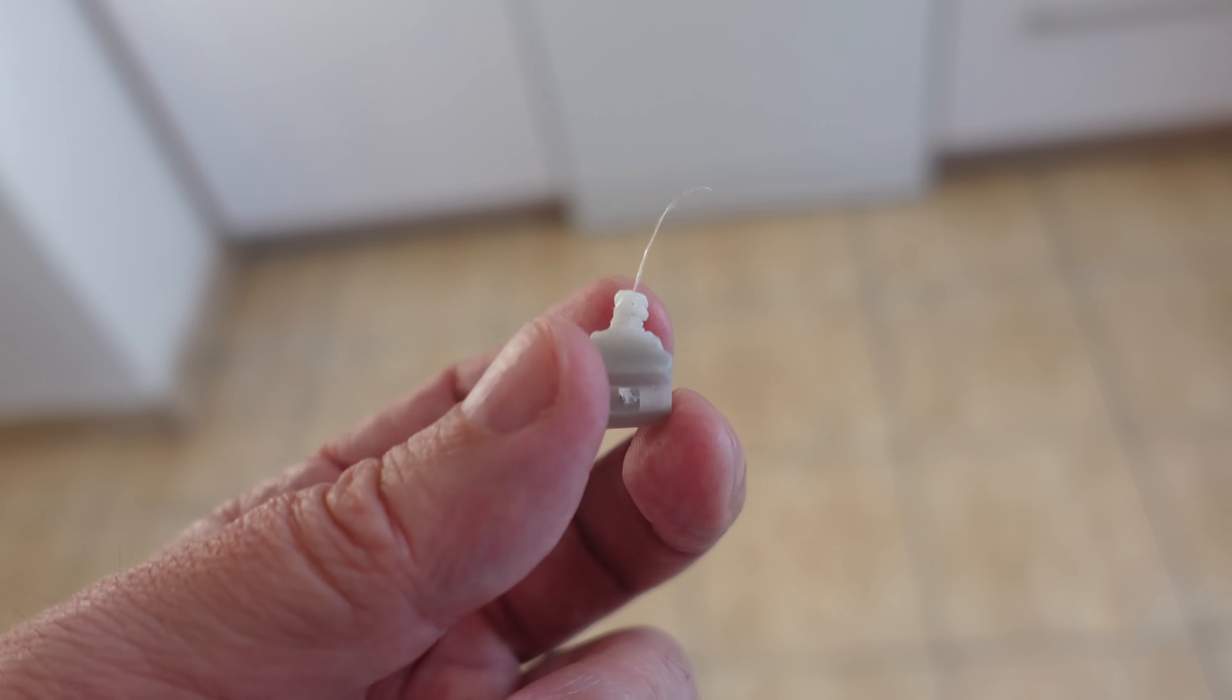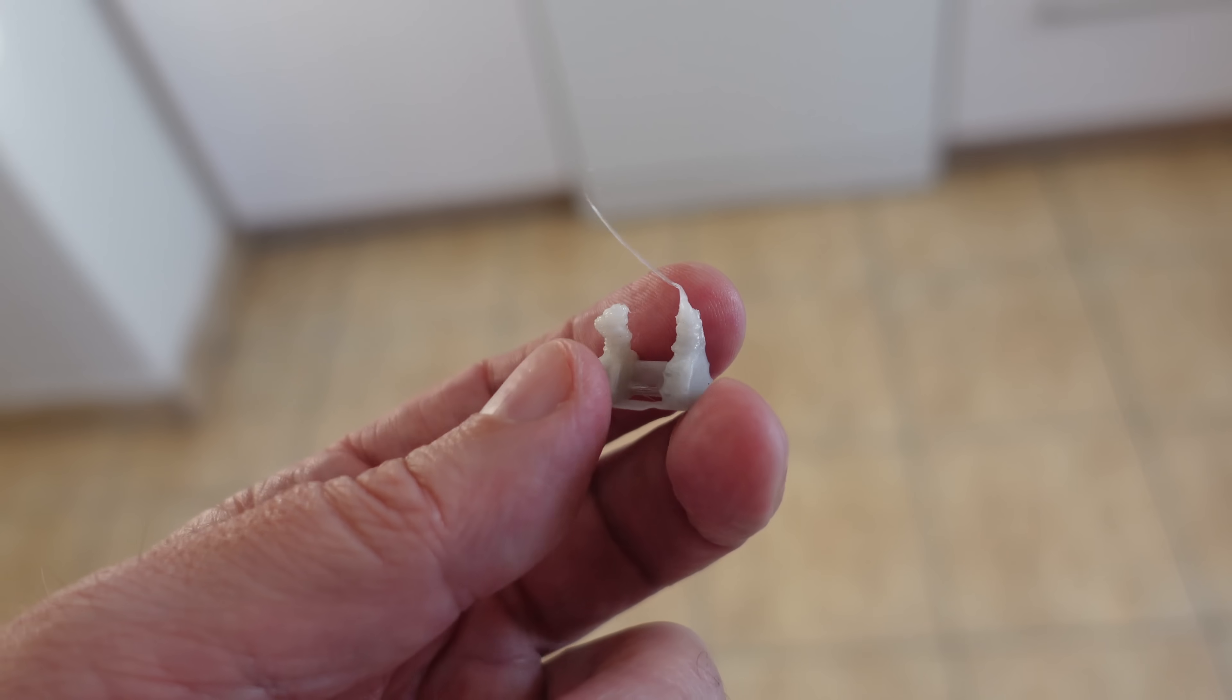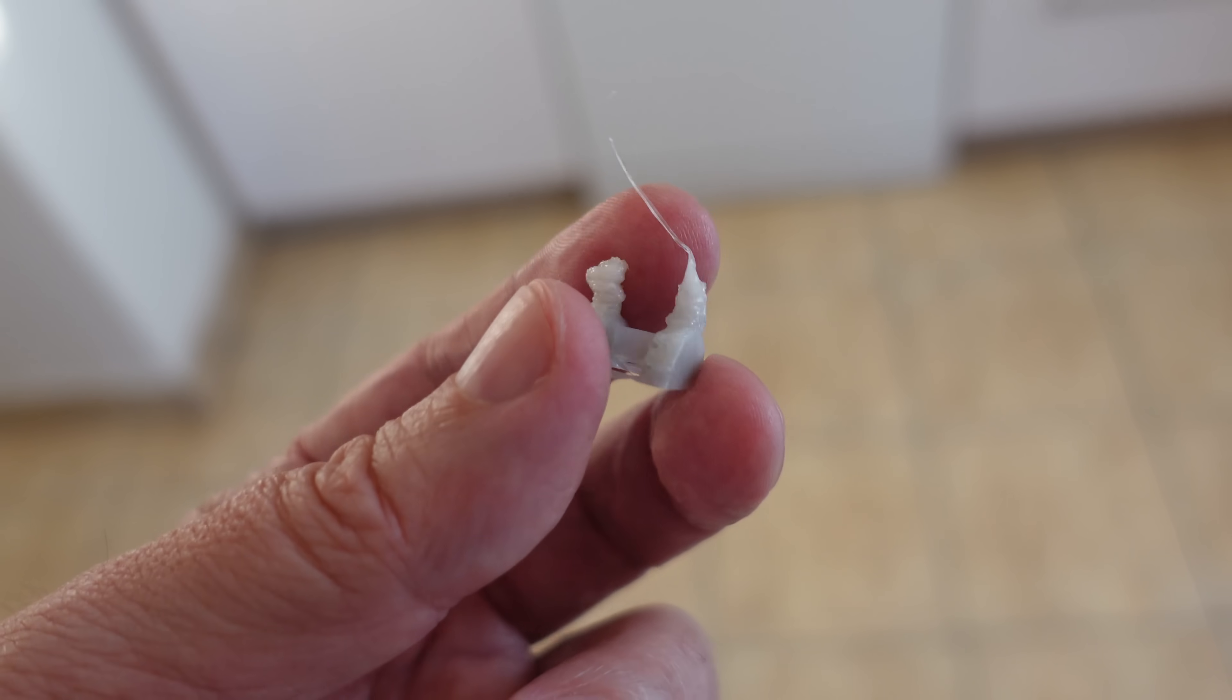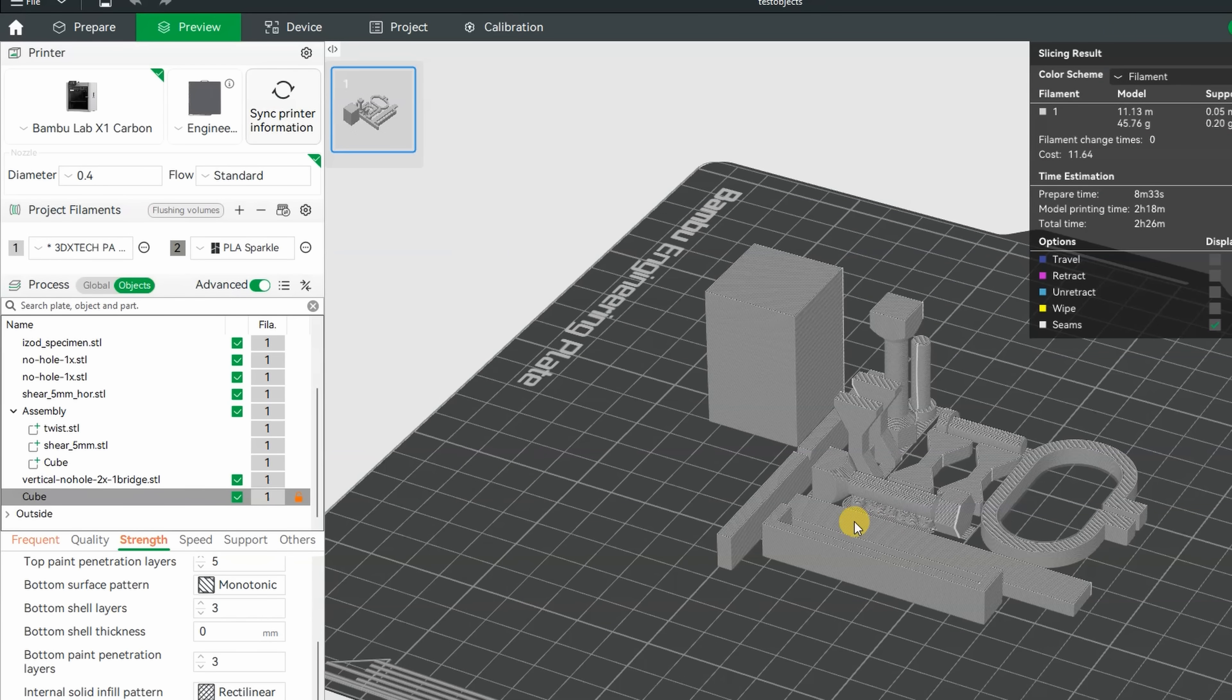I am thinking if I print all test objects at once, then it has more time to cool down, but at the end, again, I will have only one test object, which will be over melted. Maybe I can add some bigger object next to it. This is the profile I got from them, 270 degrees Celsius on the nozzle, this is one of the changes I am doing here. And the maximal fan speed I increase to 25, and only 4 is the maximal flow. And here you can see that additional box test object to have more cooling time for that vertical test object.